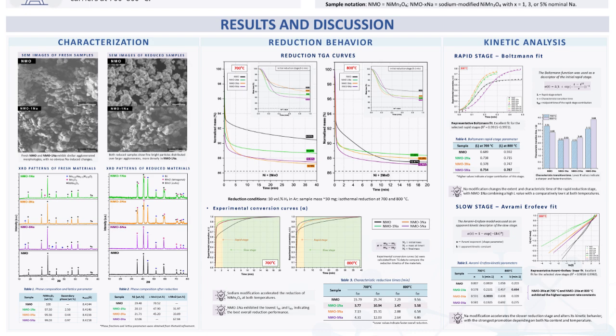All sodium-modified samples reached high conversion earlier than pristine NMO. The strongest overall improvement was observed for the 1% sodium sample. At 700 degrees Celsius, the time to reach 90% conversion decreased from about 15.8 to 3.8 minutes. At 800 degrees Celsius, it decreased from about 7.3 to 1.5 minutes. Importantly, increasing sodium content beyond 1% did not further improve the overall reduction performance.